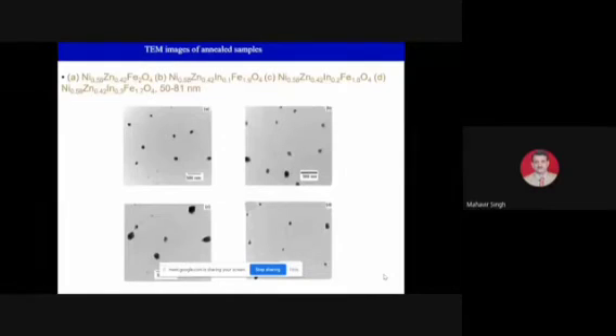Next, please. So again, the surface is controlled and the size and shape are controlled. This reverse micelle is also very important if you want to fabricate excellent magnetic nanoparticles. But the negative part of this technique is that the yield is less. If you need a high yield product, then you have to choose some other method. But if you want a low yield product, then this method is very useful, where we can use surfactant. By adding the surfactant, we can control the shape, size and morphology, and we can easily achieve SPM also. Next, please.